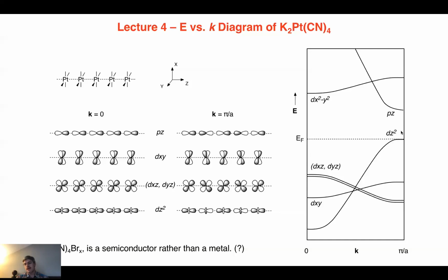That is the band gap in this material. All of these orbitals are empty. All of these are filled. So you have a band gap in this material and a Fermi energy that fills this guy all the way to the top. This is a semiconductor because of that gap and because the Fermi energy sits right in that gap. Okay? Is that clear?